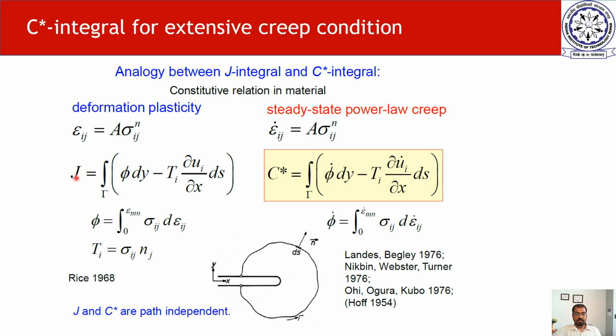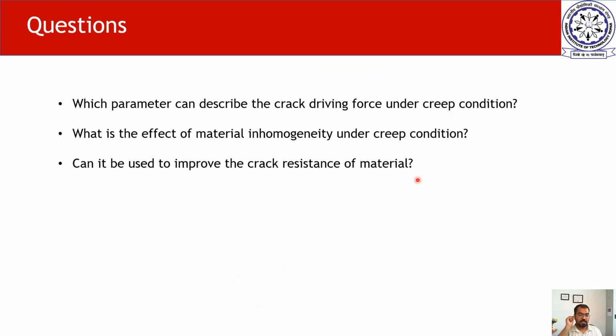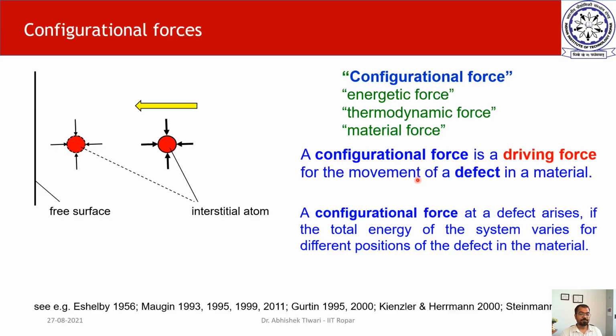dJ by dt, if you take the derivative of J integral with respect to time, you will have 4 terms, and therefore dJ by dt is not equal to C star. But dJ by dt will define the rate of change of crack driving force, at least for some ideal conditions. So the question is, which parameter can be used to truly define the crack driving force under creep condition? Second question is, does material inhomogeneity give the same effect to a crack under creep condition also, and can we use that to improve the crack resistance of the material?